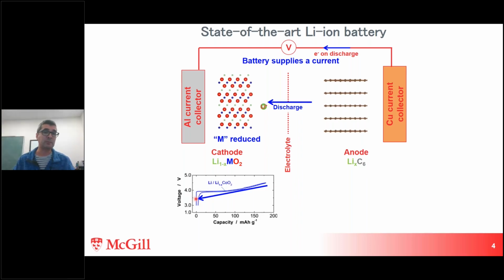And there are a number of important features on this curve. The main one from a sustainability point of view, especially when we talk about grid storage, is efficiency. So the area underneath this curve is the energy that the battery can store. And so on charge here, the area is slightly larger than on discharge, right? This curve on discharge comes a little bit lower in voltage and stops a little bit before zero. So if you take that ratio, it's actually about 90%. So lithium-ion batteries are 90% efficient. So if we're taking energy from a solar panel, 90% of it goes back in the grid when it's needed. So this is a really important property. And when you compare to other technologies, this needs to be taken into account.